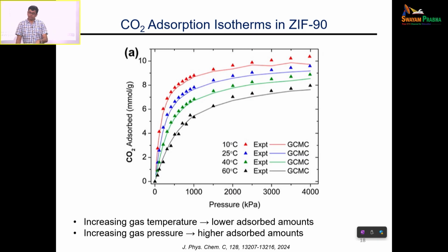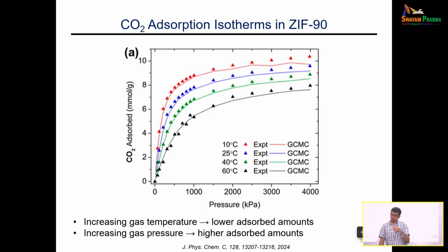What you are seeing here is not the impact of a single molecule adsorption. Like I said some time back, pressure matters. High pressure, more species interacting. Low pressure, fewer species interacting. So if you have more species interacting, of course capacity is also going to change. So this is not interaction strength like I had spoken about earlier, this is capacity. If you increase pressure, capacity increases, or the adsorbed amounts increase, and that is naturally expected. That is what your adsorption isotherms show, right? So this trend of it increasing and then tapering off is not unexpected. What was the temperature impact?